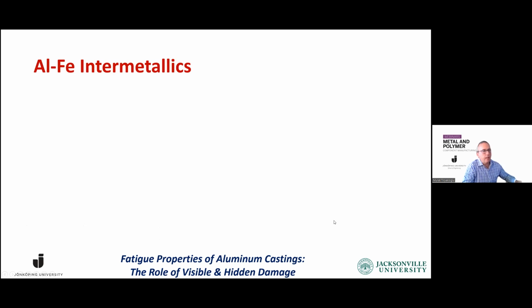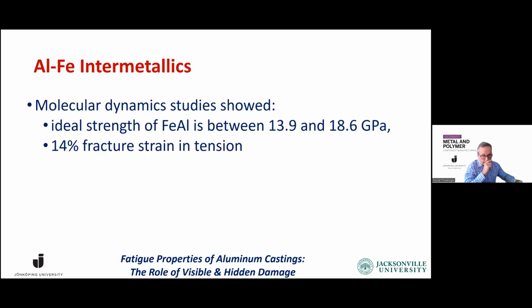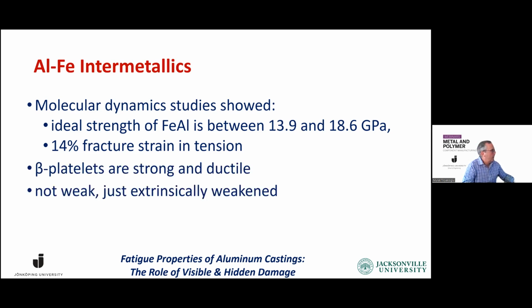So if you look at the aluminum iron intermetallics, there are some molecular dynamics studies that show that the ideal strength of these particles is between 14 and 19 gigapascal, way higher than we think they are. They are not weak, they are pretty strong. And they should have about 14% elongation in tension. So they are not brittle either. They can be very ductile. They are strong and ductile. So the only reason why we see them cracked is not because they are weak, but because they are extrinsically weakened by the invisible damage.